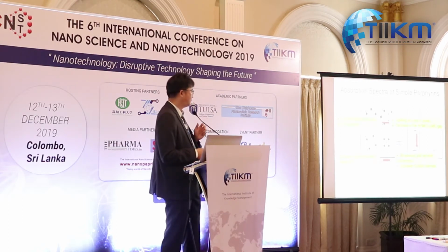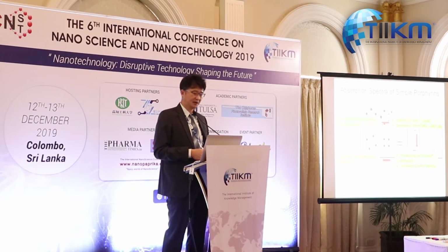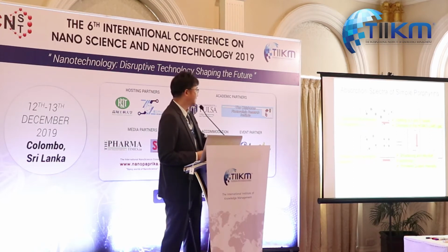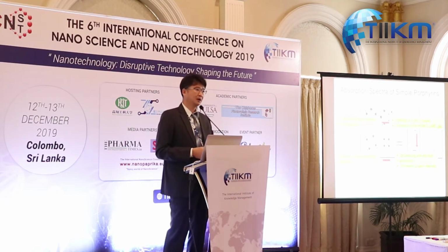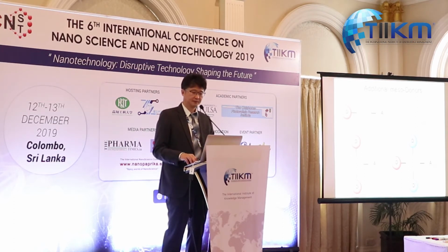Unsymmetrical extension of pi conjugation causes splitting of pi and pi star levels and a decrease in the HOMO-LUMO energy gap, leading to broadening and red shift of absorption and increased Q band relative to that of the Soret band. In such a case, the light harvesting property is enhanced. So YD2 is based on a push-pull structure. To increase the unsymmetrical extension of the pi system, we put more than one donor on the porphyrin.